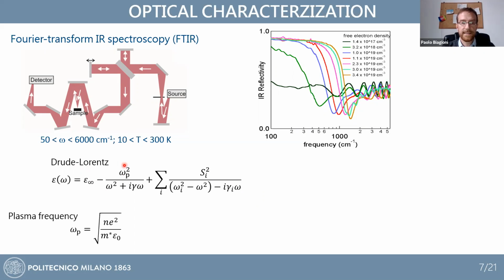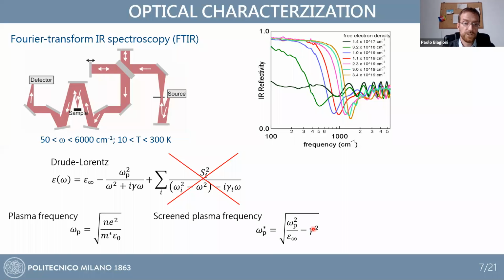And the numerator here in the Drude term is what we call the plasma frequency. And as you see, this scales as expected as the square root of n over the effective mass. Now, if you choose your semiconductor material properly, you can imagine that you are far away from absorption transitions, because otherwise you would have a poor material in terms of the losses. So let's imagine that this term does not play a significant role. So we can imagine that we use this formula, which is indeed used very often in the literature to fit spectroscopic data from semiconductor films. And here you can see that the zero crossing of the real part of the dielectric constant occurs for a specific frequency, which is actually different from the plasma frequency, mainly because it takes into account the screening of this epsilon infinity polarizability.